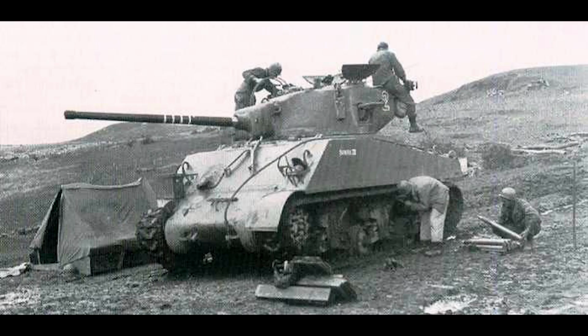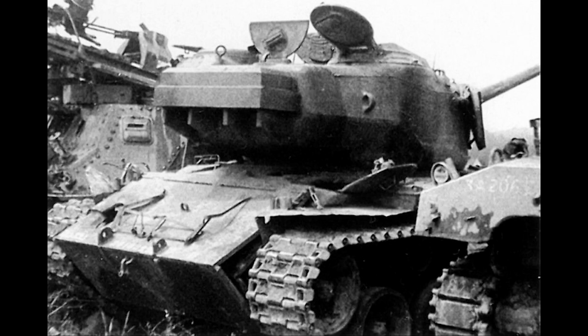They would add 1.5 inches of rolled homogeneous armor plate to the M4A3's frontal hull and sides, increasing protection from 2.5 inches to 4 inches on the glacis plate, and from 1.5 inches to 3 inches on the sides. But armor thickness alone didn't tell the complete story. What mattered was effective thickness, the actual protection provided when you accounted for the angle of the armor plate. The M4A3E2 used the newer large hatch hull with a glacis plate angled at 47 degrees from vertical.